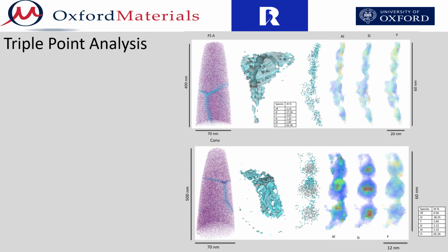The triple point at the top of the slide, coming from a flash-sintered anode specimen, demonstrates a homogeneous distribution of segregating elements. The triple point at the bottom of the slide, coming from a conventionally sintered specimen, demonstrates regions of relatively higher and lower silicon segregation, while the segregation of the other 2 impurities is relatively homogeneous. Once again, due to limited sampling, no relationship between triple point nature and sintering can be drawn.